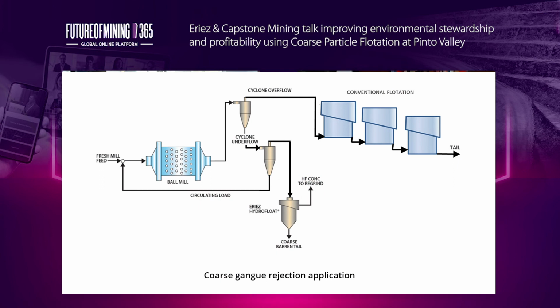In this application, the HydroFloat is put inside the closed loop of the secondary mill and acts like an ore sorter. In the coarse gangue rejection application, the mill output goes to a two-stage size classification system, shown here as cyclones, where the fine stream reports to conventional flotation, the coarse stream reports back to the mill circulating load, and the middling stream reports to the HydroFloat. This allows an increase in the grind size, reduction in power, and generation of a separate coarse and fine tail.